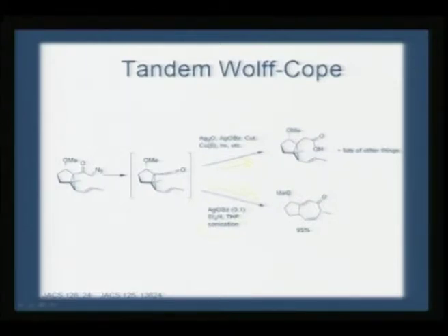In both cases they have used silver oxide as catalyst. You can see that there is conversion which is highly selective and with a very good yield if you are using sonication, whereas without sonication you seem to have a different product, also with a lot of other side products. Therefore we can say that you can look for name reactions which are highly selective if you use sonication, and for more details you can resort to this reference, because I am not essentially laying emphasis on the organic reactions.